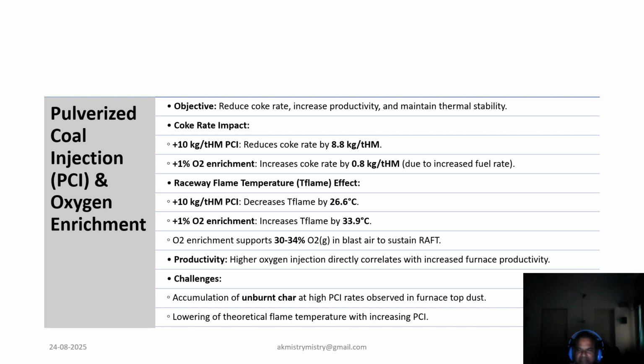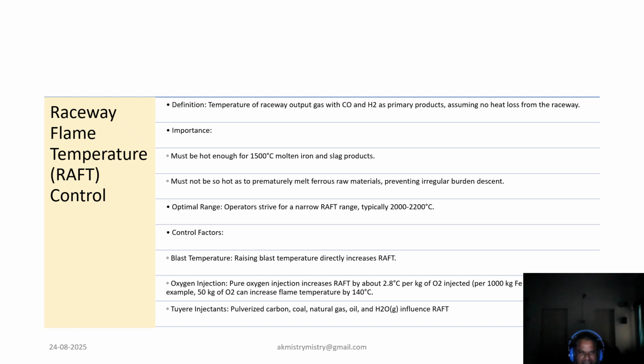Now, coming to our next slide, which is about maintaining a stable raceway flame temperature, which is very important during the course of pulverized coal injection as well as oxygen enrichment. So RAFT is a paramount, important index. It's the critical temperature of the gas leaving the raceway, impacting molten iron and slag quality. This temperature must be hot enough for the 1500 degree centigrade molten product, but not so hot as to melt raw material prematurely, which would disrupt burden descent. We also see cases where excessive flame temperature creates a problem of asymmetric burden descent in the blast furnace.